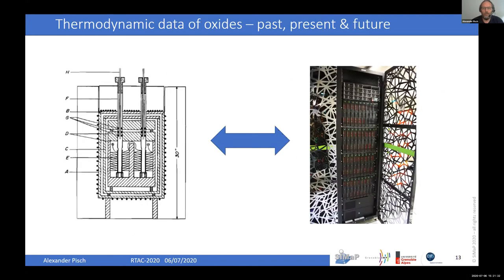And now comes the important new stuff. We can do calorimetry by working with numerical calculations, which was not possible before. I also consider this a numerical calorimetry, because in real calorimetry, you measure the heat of a compound with respect to the constituents. In numerical calorimetry, you do the same. The only thing is that you do the calculations. So you calculate the internal energy of the compounds and the constituents, and by difference, you also get the energy of formation.